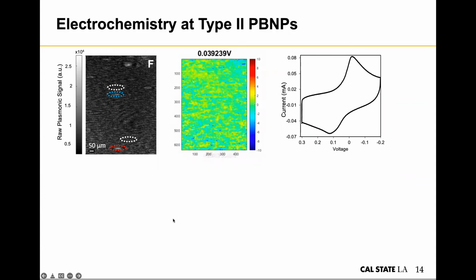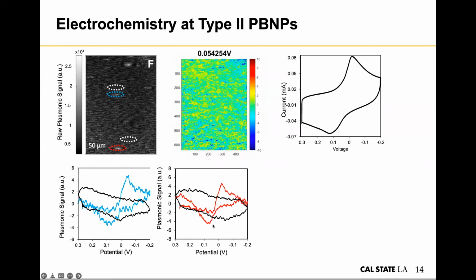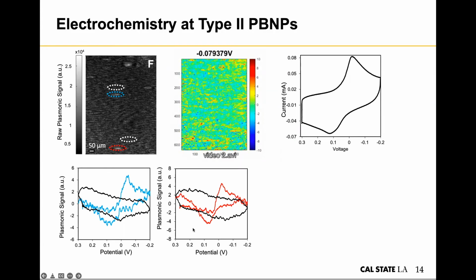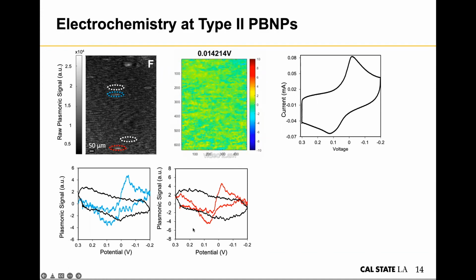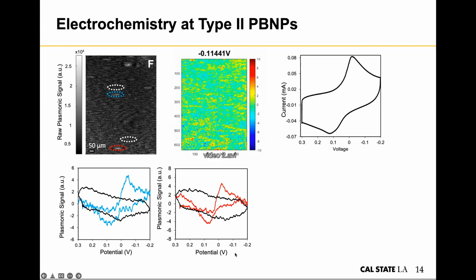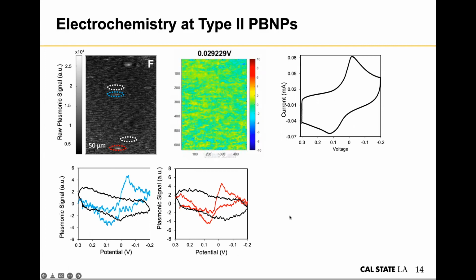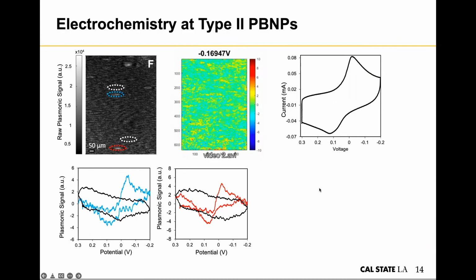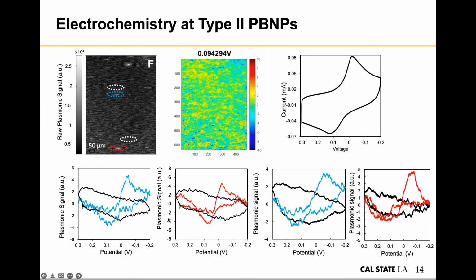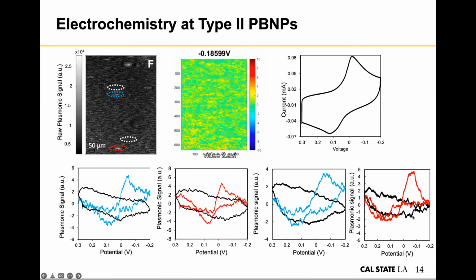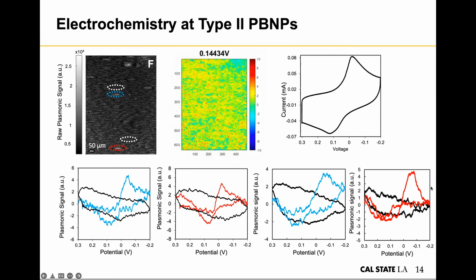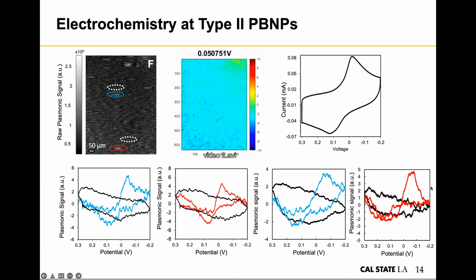And then when we extract signal from individual particles, we got very distorted CVs, and the signal is much weaker than type 1 Prussian blue nanoparticles. We also tried varying the amount of PVP present in the initial synthesis method, and these two are with 3 grams PVP, and this is with 10 grams PVP. And you can see that with 10 grams, with more PVP present, you have even more distorted CVs.